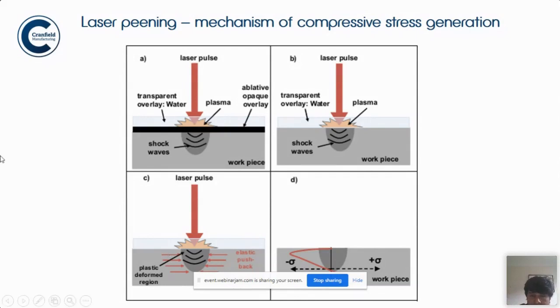magnitude of stress, and you can see here that you create a very large compressive stress. But remember, there will be a balancing tensile stress. But if the balancing tensile stress is created in a region which is not affected by the crack propagation, then it really doesn't matter. So when you create such a process, you have to be a bit mindful about how the balancing residual stress will be created.